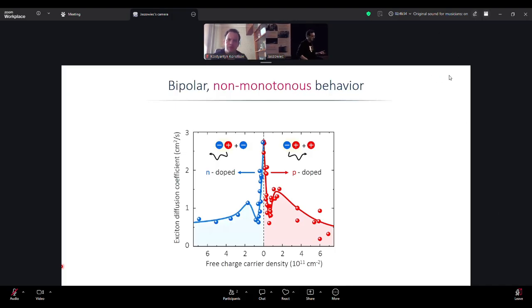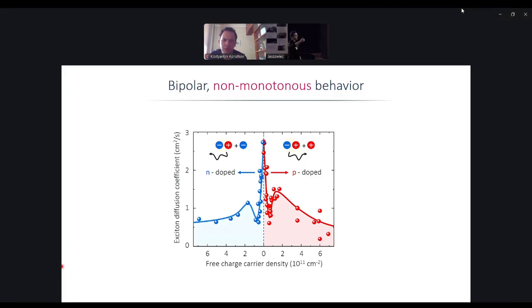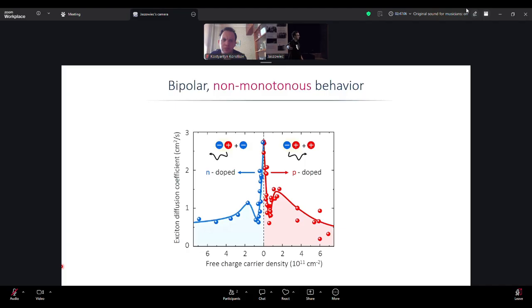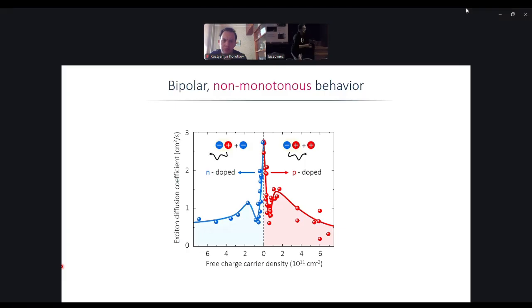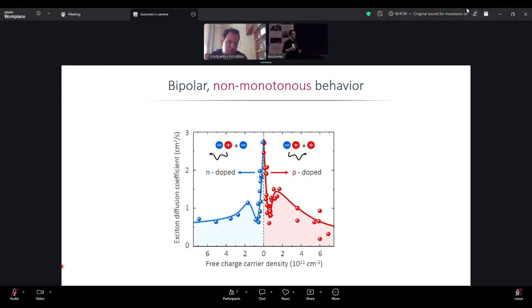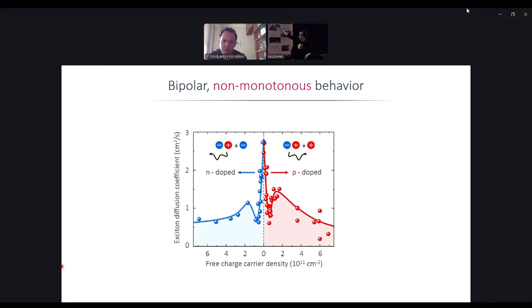And in this case, as we have quite often in physics, when what was treated perturbatively before is now a new quasi-particle, the interaction of the trion with the remaining electrons is suppressed. One way to think about it: if you have an electron and an exciton, they can come very close and interact with exchange. If you have a trion, it will repel the electron due to long-range Coulomb, and the scattering is very inefficient. This result, that the scattering of electrons with trions is inefficient, has been known for a long time, from quantum wells in zinc telluride, I think, in the 2000s. And here it leads to the recovery of the transport in this unusual case. Okay, this was a very quick explanation of it.